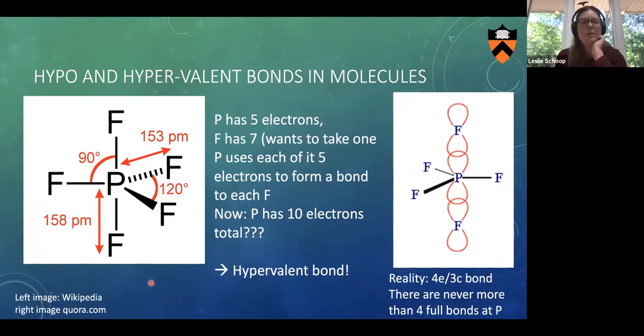So here's an example of a hypervalent molecule, phosphorus pentafluoride, where you have five bonds to the phosphorus. If you count two electrons per bond again, this is 10 electrons around the phosphorus, also not eight. So something is not right. One way to describe phosphorus pentafluoride and its bonding is to say you have a four electron three center bond along this extra line, where four electrons distribute among these three centers, which again gives some degree of electron delocalization and reduces the count formally to eight.